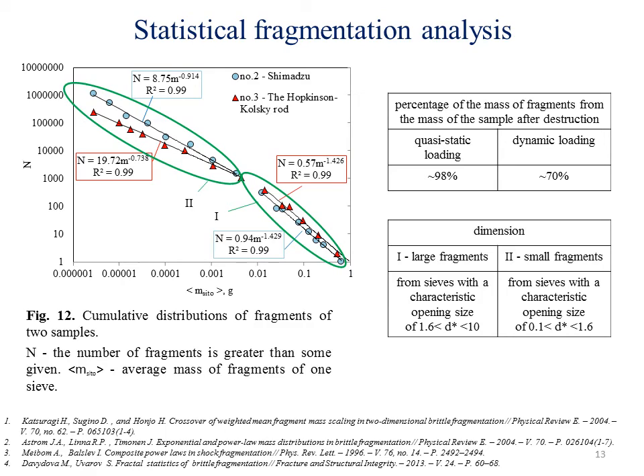This slide shows the cumulative fragment distributions for 2 samples obtained under quasi-static, number 2, and dynamic loading, number 3. The curves have 2 slopes. Each slope is described by a power law, which is typical for the destruction of brittle materials. For large fragments, the power in the law was the same for all samples. For smaller fragments the degrees were different. Part of the curve runs below. This is possibly related to the formation of these fragments as a result of the large fragments breaking.